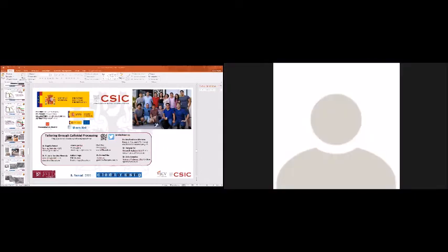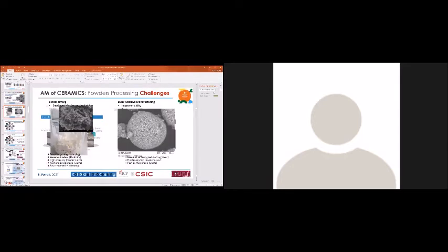Thank you, Begoña, for a very nice presentation. This is my main topic as well, so I enjoyed it really a lot. I have a question about binder jetting and what you mentioned, granulation for binder jetting. We also have some experience on this, and granulation improves flowability of the powder, so this can be a really important advantage for the processing. But on the other hand, we experience with granulation a lot of issues because the microstructure, so the distribution in the powder bed, is not homogeneous, which creates problems both during printing for the distribution of the binder and also for sintering, because the material doesn't sinter homogeneously in most cases. Do you have any tricks or suggestions maybe to improve these problems?